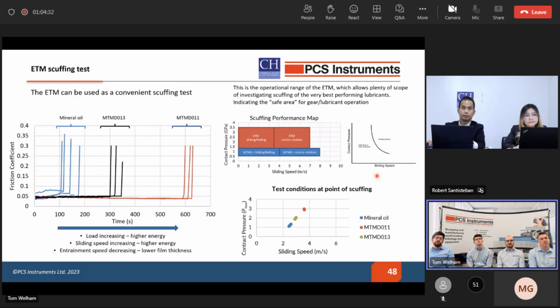Another example, as mentioned, was looking at scuffing. Using a time step on the ETM, we can ramp load, sliding speed, and entrainment speed to increase the severity of the conditions seen in the contact. This shows 3 different oils, and over time we're ramping these parameters as shown here, and we can see, with very good repeatability, the point at which scuffing occurs, and how that can be picked out between these different oils.